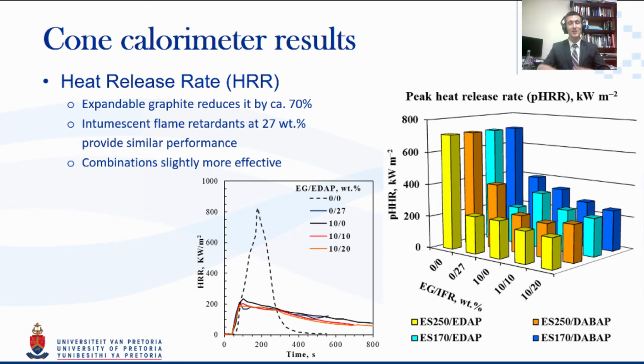So we actually achieved some really good results here, in that all of these materials, when they're used together in a binary system, delivered thermal behavior that exceeded that of the material itself. The expandable graphite reduced the peak heat release by a substantial amount, and these intumescents in combination with that big reduction then proved even more effective.